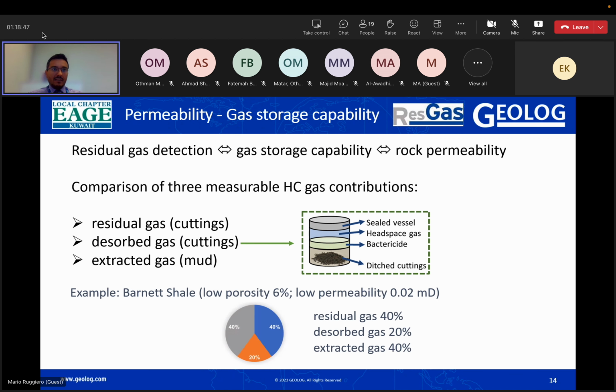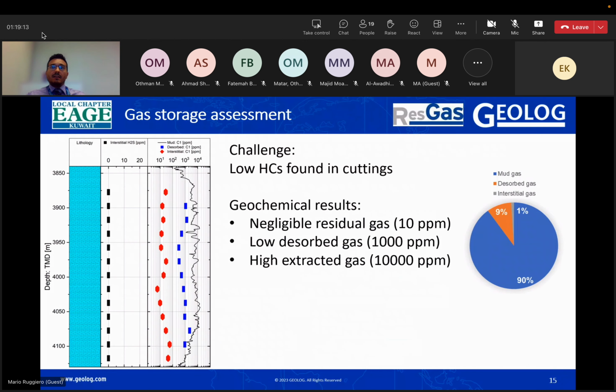So, for example, in the Barnett Shale, which has a very low porosity and low permeability, the common behavior is that the Barnett Shale will release around 40% of the gas in the mud gas, and another 20% will be desorbed in the headspace, but the remaining 40% will stay in the pores because of the low permeability. How can we use this?